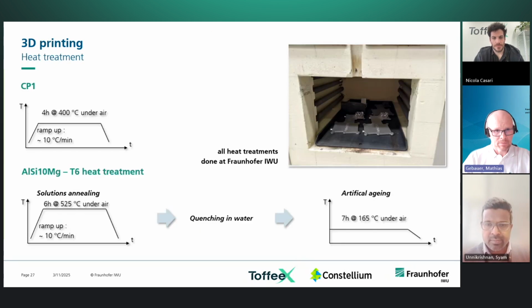And from the 3D printing, we went to the heat treatment. Sham told you about the heat treatment already at the beginning. This just gives you an idea of the rather quick and simple heat treatment we used for CP1. It's 4 hours at 400 degrees. That's rather simple. For the AlSi10Mg part, we went with the conventional T6 heat treatment. It's widely used for cast parts. We still use it at our facility. I think a lot of manufacturers or additive manufacturing providers use a different heat treatment. They also just do an aging afterwards, so they don't use a two-step T6 heat treatment. But in this case, you can see you can even have an improvement in heat treatment time.